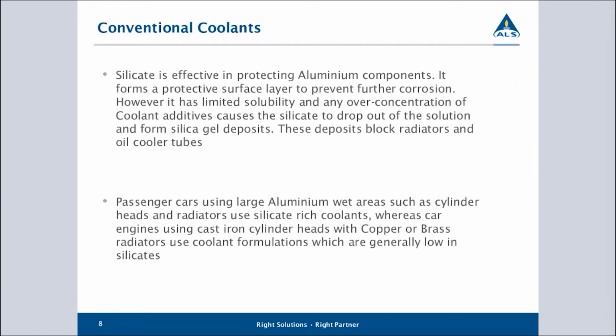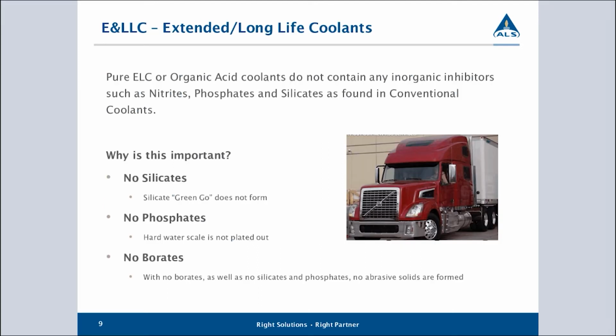If you have an engine that is primarily aluminium rather than cast iron, then the sodium nitrite doesn't work very well, and so these tend to use a silicate inhibitor. You tend to find that these have fairly high levels of silicon in the silicates in the coolant to prevent corrosion. There are problems with using silicate-based coolants. I'll get into those in a little more detail in the next few slides.